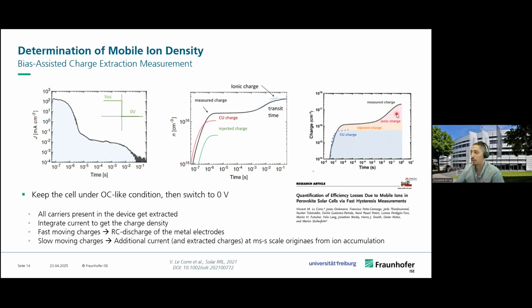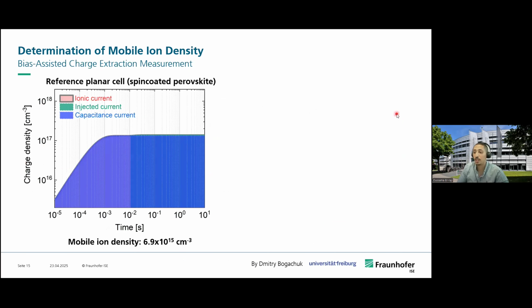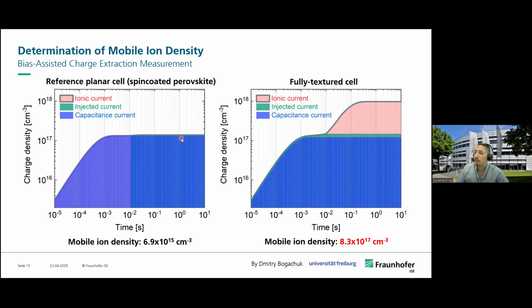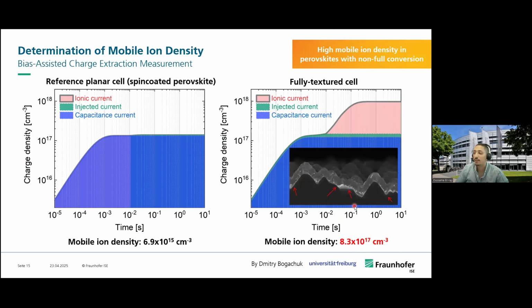So we carried out such a methodology, and we took a reference case where we had a cell with spin-coated perovskite, and then the cell with the hybrid method on textured silicon. In the reference cell, we observed that the mobile ion density was relatively low, in the order of 10 to the power 15. But when we measured it on a textured cell, we observed 2 orders of magnitude higher, so 8 times 10 to the power 17. And this we linked to the fact that, at least in the first tries of making perovskite films on textured silicon, we did not have a full conversion.